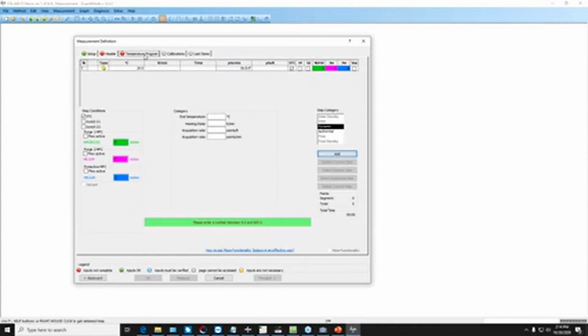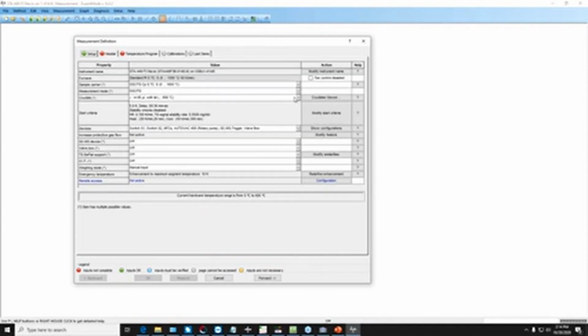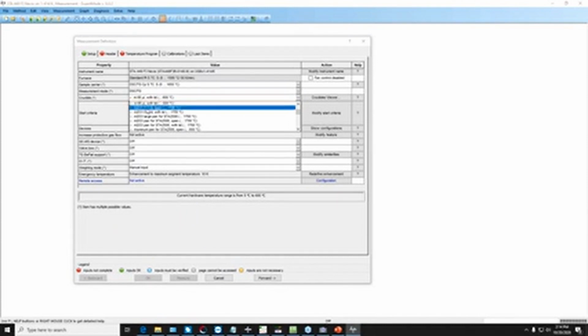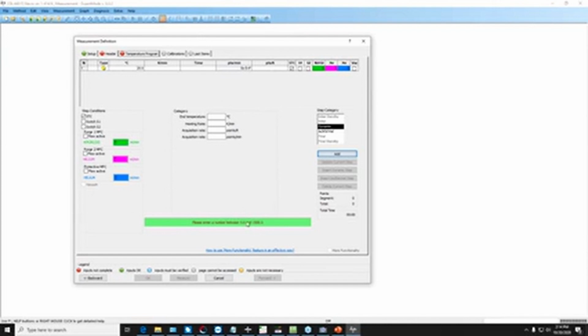So whenever you go to the temperature program page, if I wanted to create a dynamic step and put an end temperature, it'll give me what is the limiting factor. So in this case, I'm choosing aluminum, so I can only go to 600 degrees Celsius. But if I were to run with an aluminum oxide crucible, let's say, then it'll give me a higher maximum temperature. So this 1500 is my max, and that is due to the fact that my platinum furnace can only go to 1500. So the software will give you these restrictions so that you won't program a temperature that is not allowable, that might damage one component or the other.